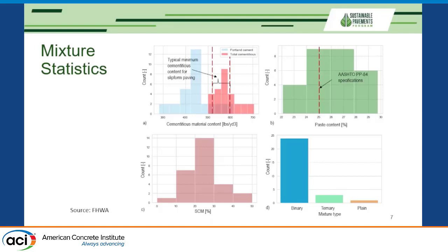Also, when we analyze the paste content, here is the line of 25% paste based on AASHTO PP84. Now it's AASHTO R101. These are concrete performance-based specifications. They recommend 25% as the maximum paste content. However, most of our mixes, 17 to be exact, are actually made with over 25% paste. In terms of supplementary cementitious materials, most mixes are using SCMs, and the contents range between 20 and 30%.